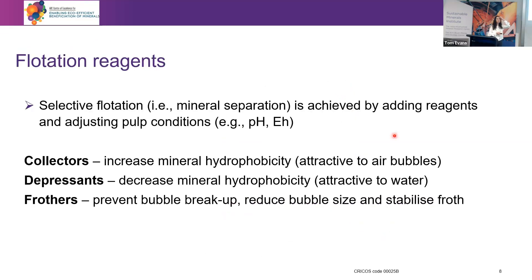A little bit about flotation reagents. There are three main types: we use collectors to increase mineral hydrophobicity for minerals we want to recover; if we don't want to recover a mineral we use depressants, which make them hydrophilic so they don't attach to bubbles; and we use frothers to prevent bubble breakup, reduce bubble size, and stabilize the froth.